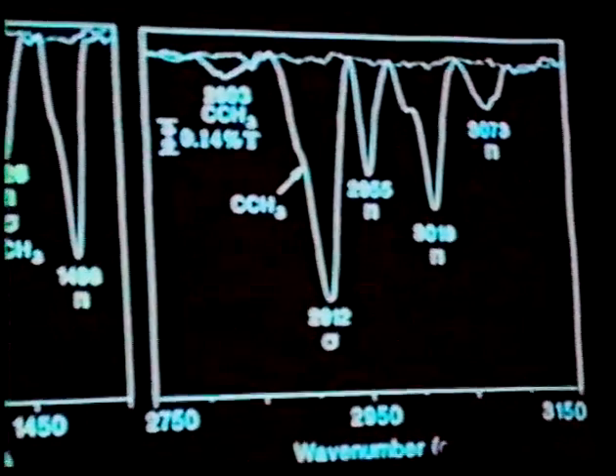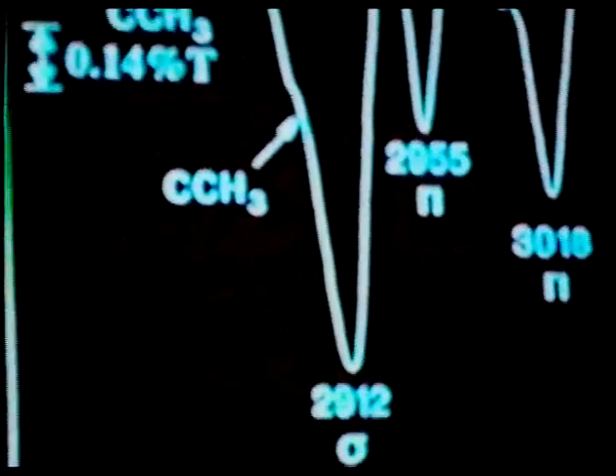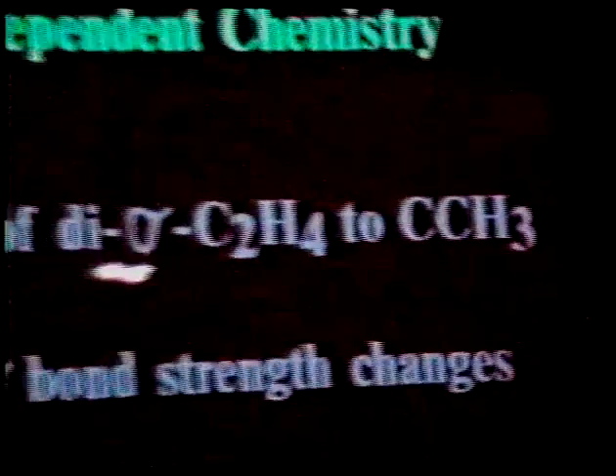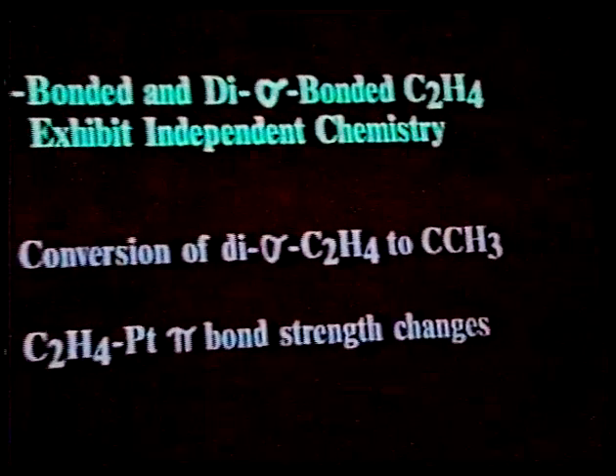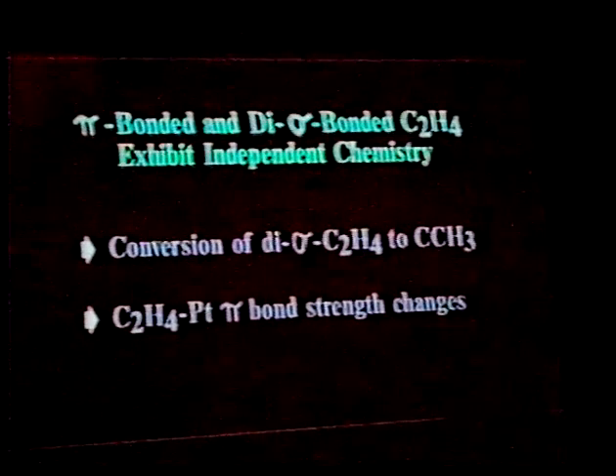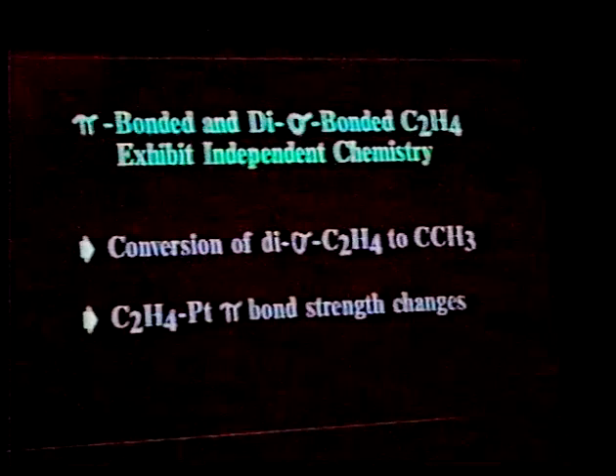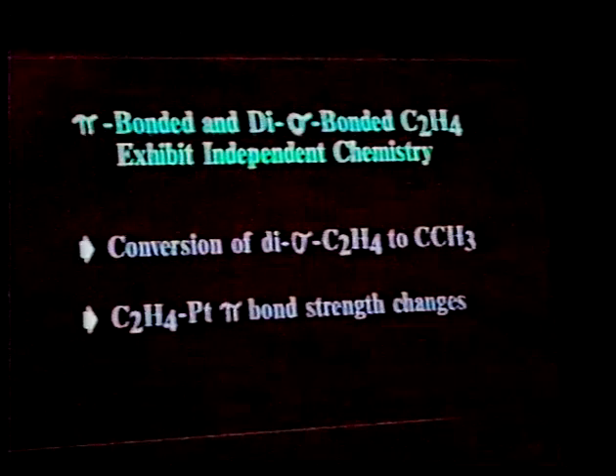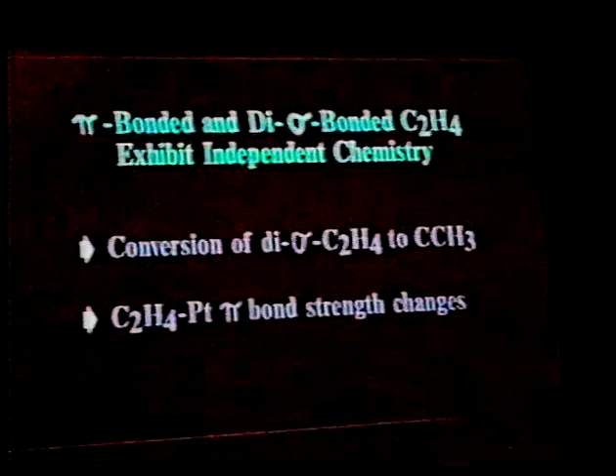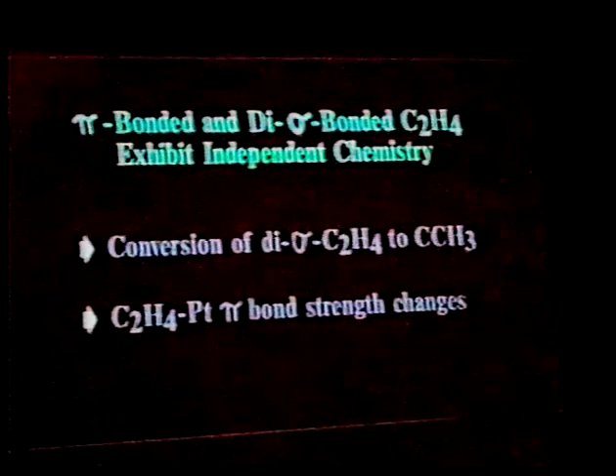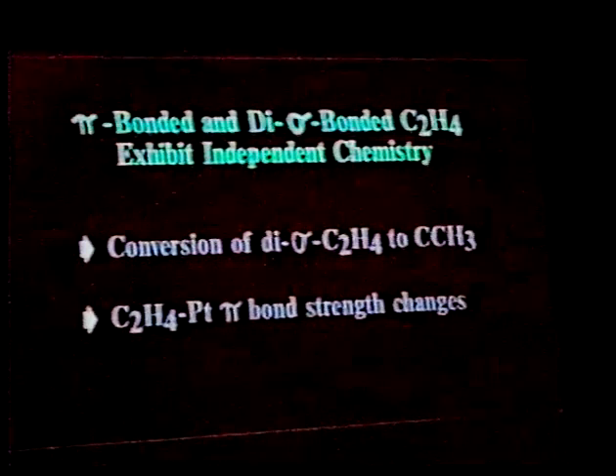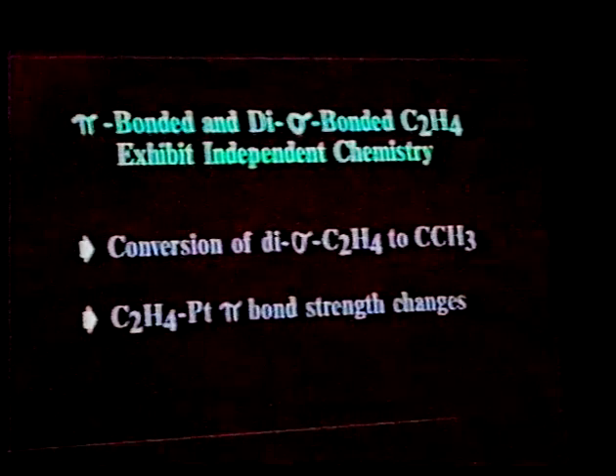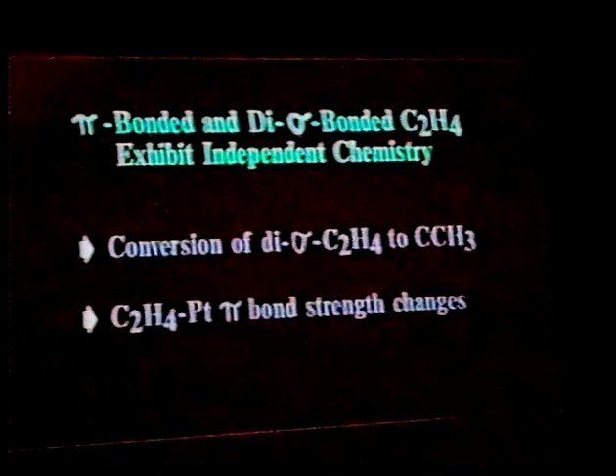So what I'd like to do now is show you how these two different principal species, the disigma and the pi-bonded species, undergo different kinds of chemistry initially on the platinum surface. Specifically, disigma is found to convert exclusively to ethylidyne as you warm the catalyst up. There appears to be no participation by pi-bonded, either as feeding into the sites that will slowly deplete the pi-bonded species and raise the amount of ethylidyne that you form. It doesn't seem to come off the particles. It doesn't seem to interfere with what the disigma-bonded species is doing at all.